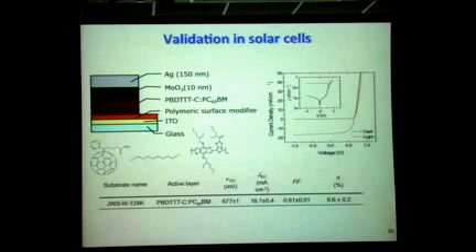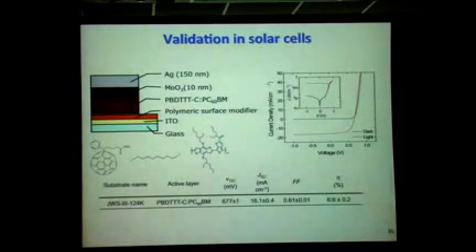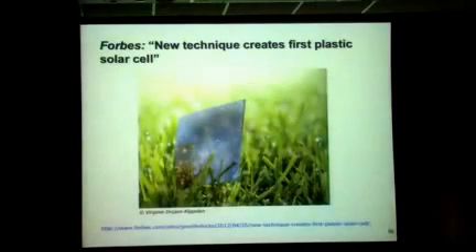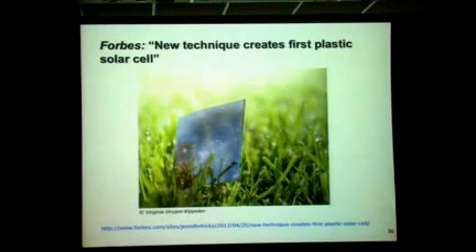You can see you can get very nice solar cells with efficiencies of the order of 6.5%. However, when we realized that you can actually use this to also modify conducting polymers and make low work function conducting polymers, we thought, okay, so we can make completely plastic solar cells. And so this is work that we published in Science last April, and there have been a lot of stories about these completely plastic solar cells.